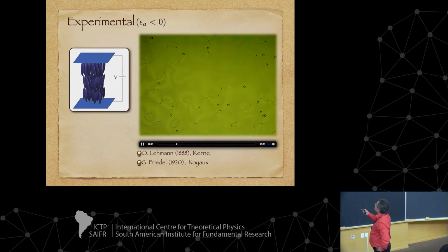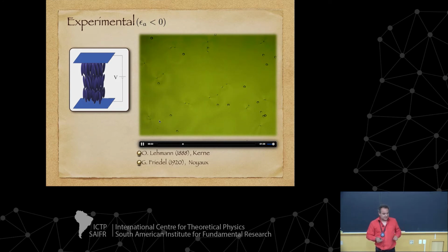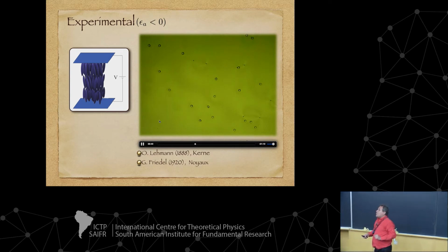The typical size is 15 micrometers, so you can see there are different charges, positive and negative, they attract and annihilate. Okay, so in this experiment, essentially, you observe a gas of vortices. They are created because the electric field induces vortices, but after that, the system tries to minimize the domain so they attract and disappear. Okay, the attraction, more or less, is 1/distance. Yeah? The interaction is logarithmic? No, it's 1/distance. It's more complicated.